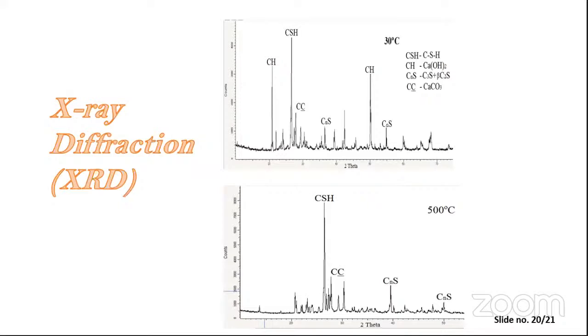And XRD is there. The peak lines indicate that it has some crystallinity, meaning the concrete is more crystalline. And we observed here that at 500 degrees centigrade, this component CH, calcium hydroxide, is completely disappearing. Maybe because of that, strength is affected.